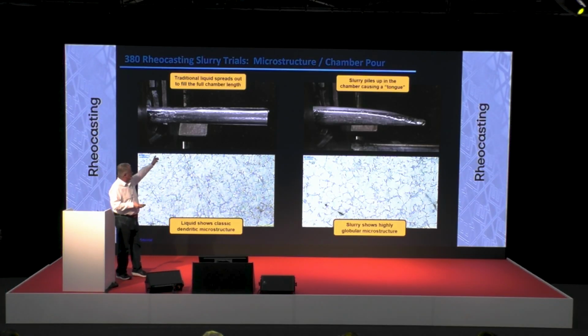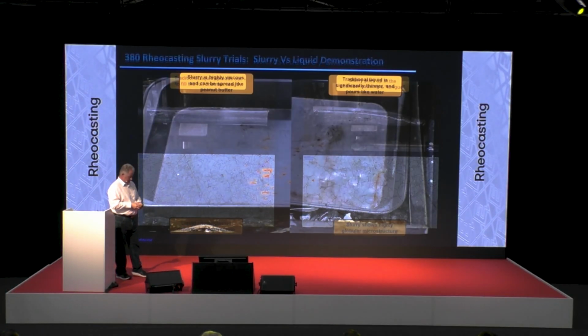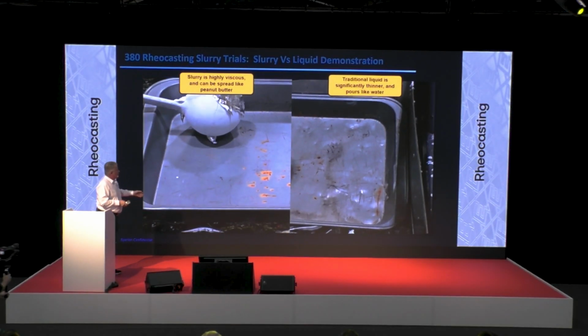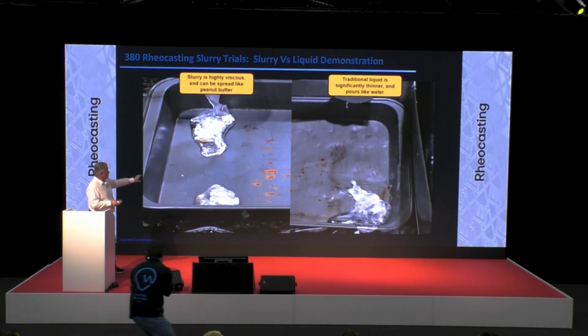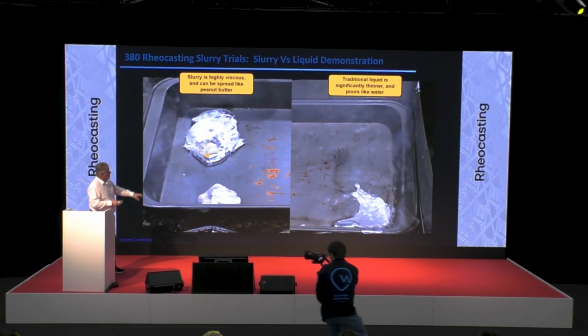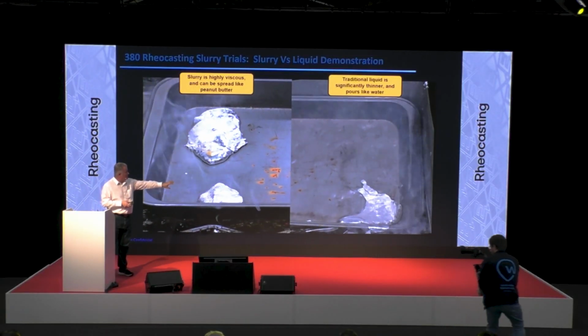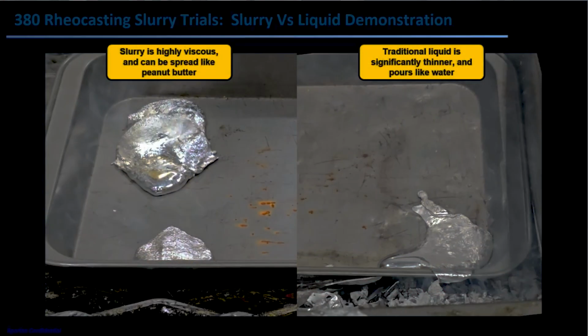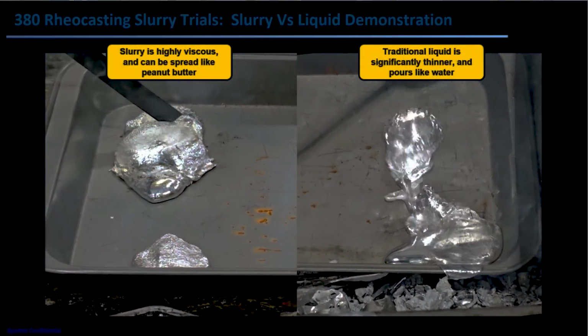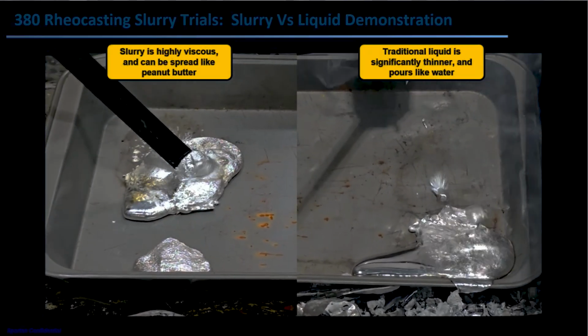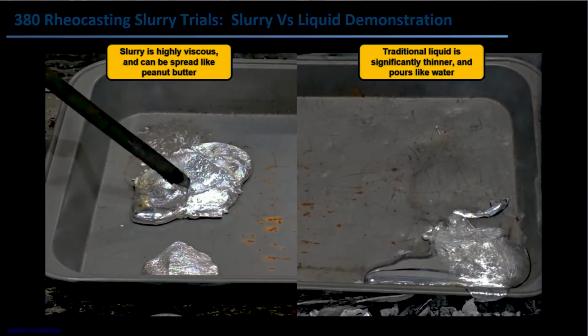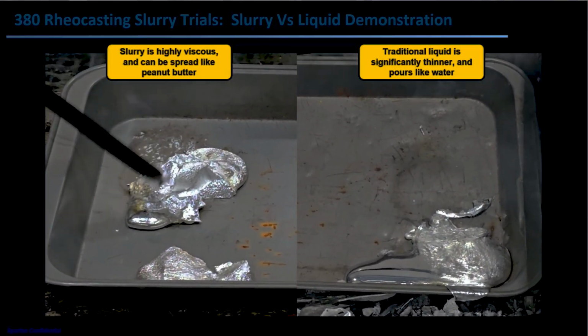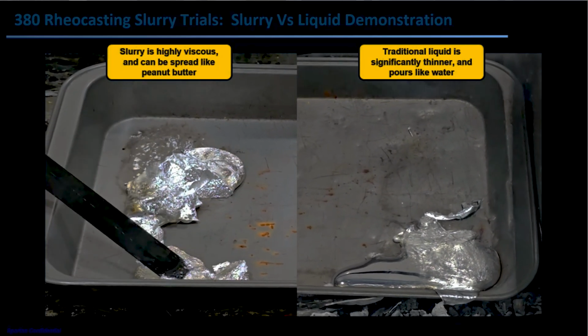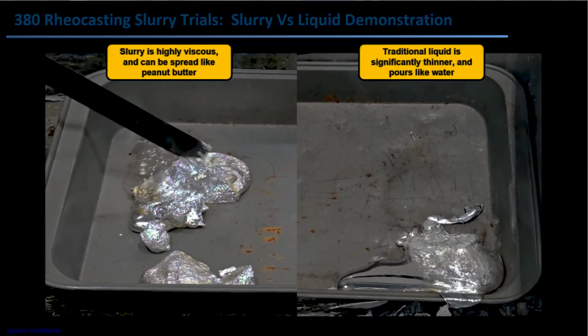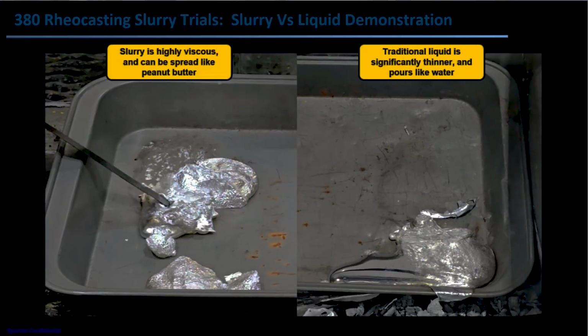And very different as you push it out of the shot sleeve. Here, you can see the difference. Apologies for the quality of the tray, but very different between liquid and the Rheocast slurry, which, even though it appears to have solidified, is still movable, so you can continue to push it through the die much more slowly, maintaining a laminar flow with the front there.